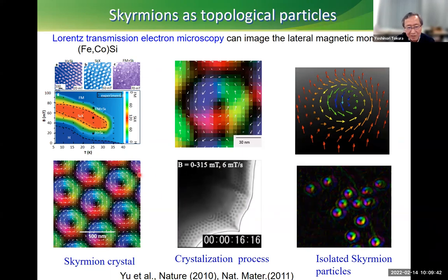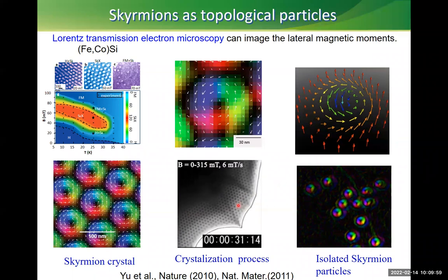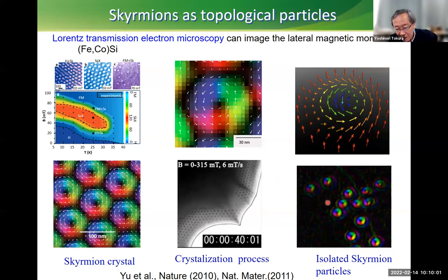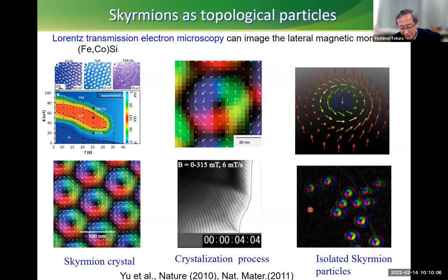Of course, this skyrmion crystal can be described by the triple Q density wave picture. But sometimes if you apply the magnetic field strongly, the skyrmion tends to evaporate, and then it's just trapped by some deficiency. So it's a trapped magnetic structure, something like a particle-like, colloid particle-like structure. This just defines the particle nature of the skyrmion.